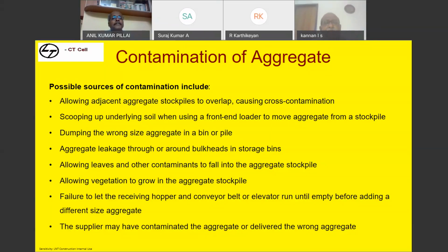Then, aggregate leakage through and around bulkheads in storage bins. Where a storage bin is there, there should not be any mixing of aggregates. There should not be any hole or gap, so that mixing does not happen. One aggregate bin may be full and the other half, and the aggregate should not flow from one bin to the other. That also you take care of.